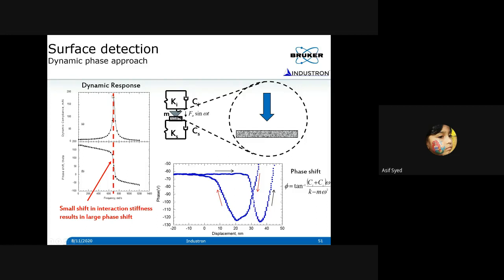And this is a very sensitive measurement technique. By monitoring the phase shift, you should be able to say whether the tip is making contact or is away from the surface. Even when the surface forces are acting, even before the material is in contact with the specimen, you should be able to feel the tip by measuring the phase shift. That's all I wanted to mention about this slide.